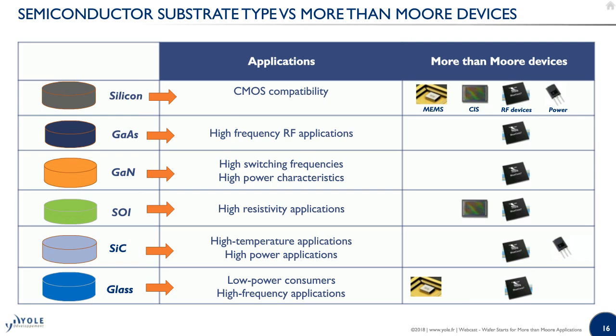Gallium nitride, for example, is interesting as a high electron mobility material for high-frequency switching. Silicon carbide will stay the preferred choice for high-temperature applications. In the case of glass materials, it's a good option for low-power consumer applications like RFID and high-frequency applications. And you have the SOI, which is basically used for high resistivity applications.